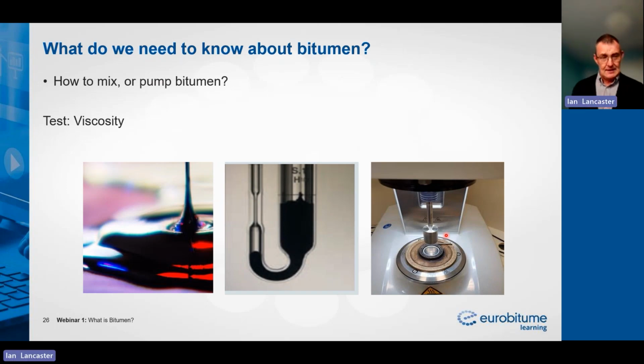However, we are starting to move now more into this type of equipment, which is known as a rotational viscometer. And the beauty of a rotational viscometer is that you can measure the viscosity of the product across a range of different temperatures and a range of different shear rates. So you can get a full profile of the behavior of the bitumen when it comes to mixing and pumping and storage using that one piece of equipment. And eventually we feel that specifications will move across to measuring the viscosity of the bitumen using a rotational viscometer.